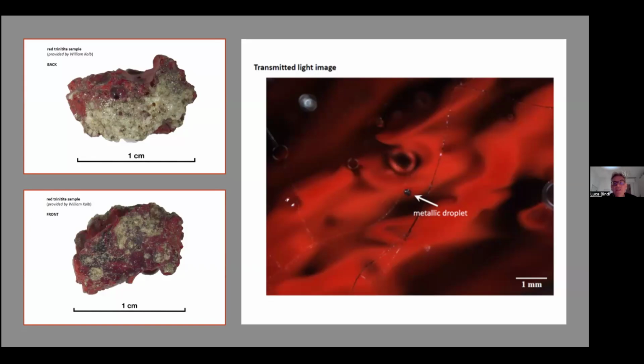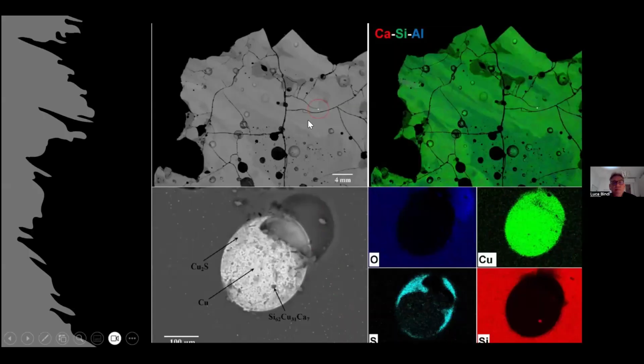But these metallic droplets turned out to be very interesting because if you look at the chemical maps, look at this. This is the droplet. This is a composite map where you can see that the silicate glass is actually a combination of the classic calcium, aluminum, silicon. But look at the blow up of the droplet. This image is important because I want to underline how careful you have to be. If you look at these kind of droplets, as was done in the past, it seems mostly composed of copper. But if you look carefully at the chemical maps on the right, you can see that on the rim there are copper sulfides.